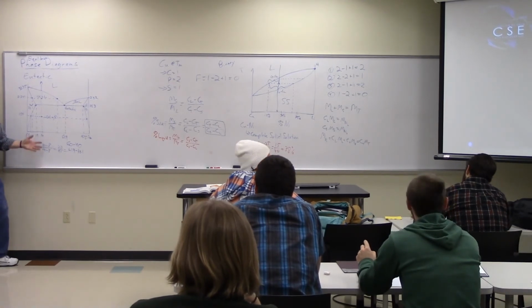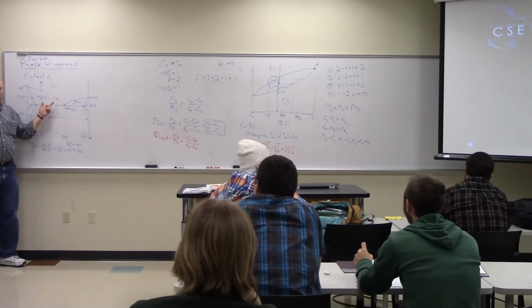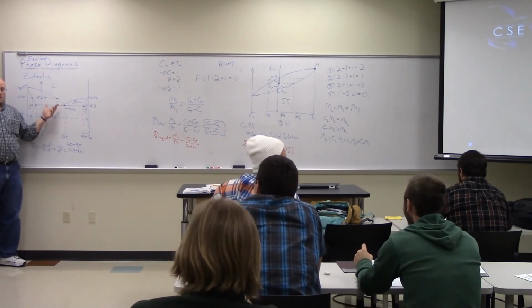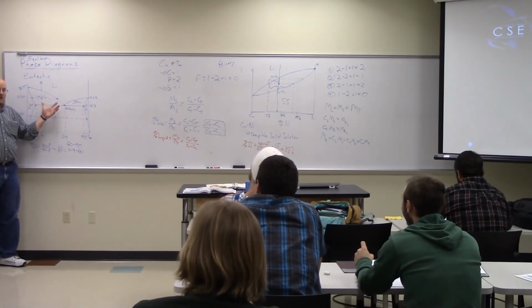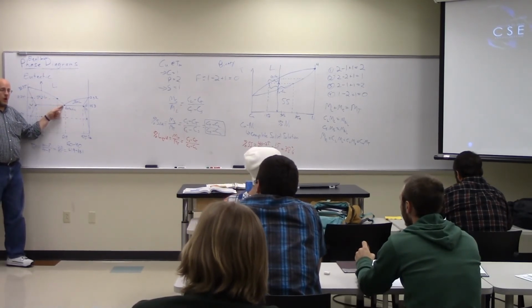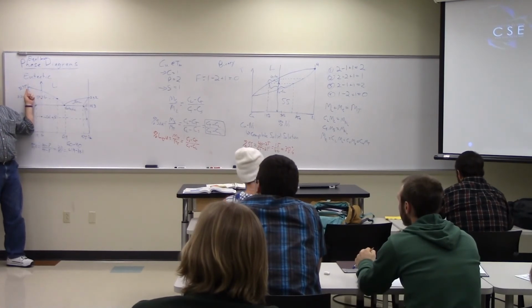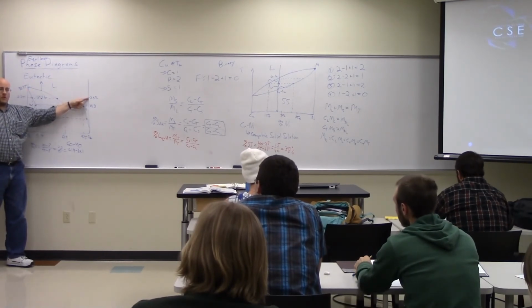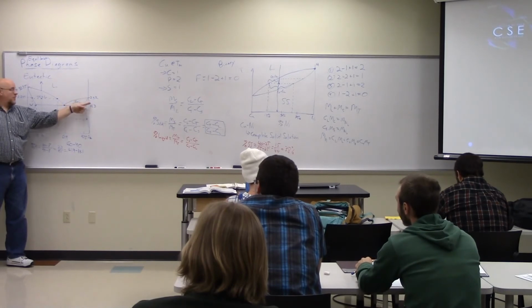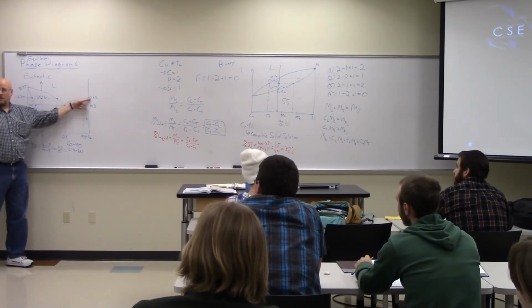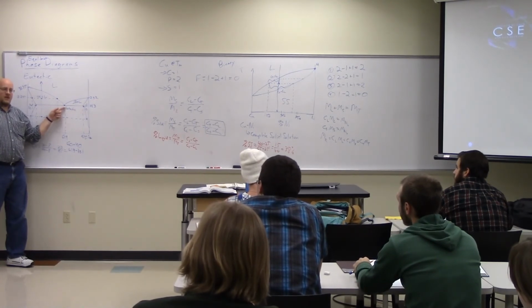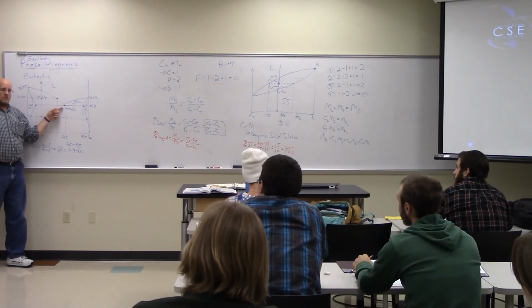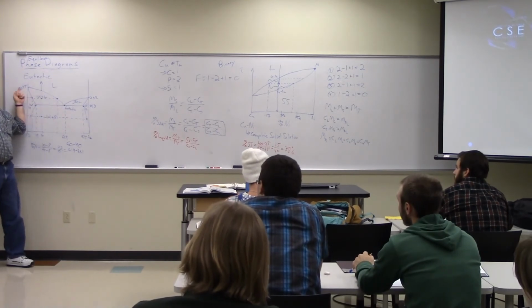So that's why we use solder. The whole purpose of using lead tin solder is that this melting point is lower than either of those. We could use pure tin solder if we wanted to. It would work, but we have to heat it to 232 degrees C. The advantage of lead tin solder is we only have to heat it to 183, so we don't have to heat it as hot to get it to work. We use pure lead too, but it's 327.